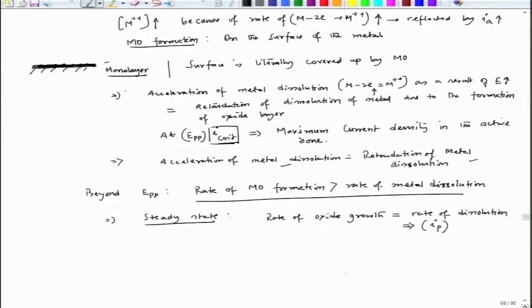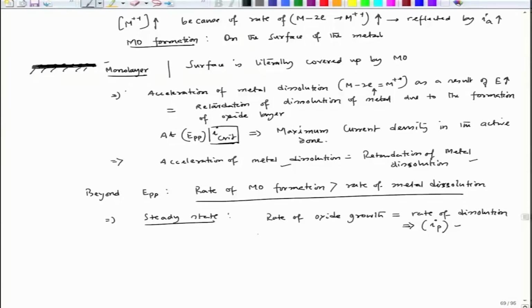So, after crossing I critical, current density reduces because more and more oxides are forming on the surface, and at a certain location the rate of oxide growth will be just equal to the rate of dissolution, and at that point I will experience I p, and that potential point will be called E c p, or complete passivation potential. So, this is the steady state. Now, what happens? At I critical, the retardation of metal dissolution due to the metal oxide formation is equal to the acceleration of metal dissolution due to the anodic polarization.